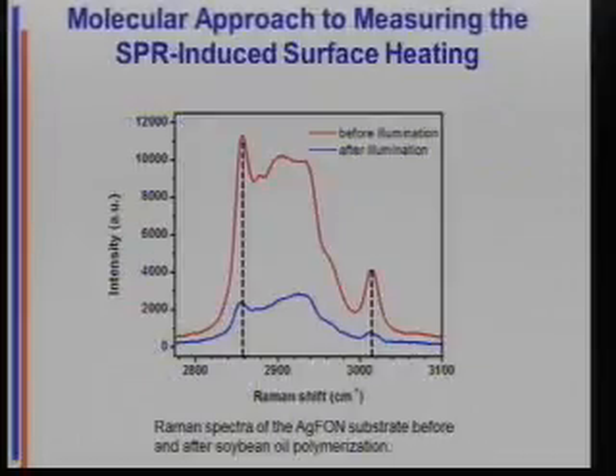And so then we come to how do you figure out what the temperature of the substrate surface is? We're talking about little bitty hotspots on little bitty nanoparticles. It's not a thermometer problem. It's not a thermocouple problem. So the answer turns out to be we're going to bracket it with chemical reactions that have known onset temperatures. Because people have cared about food oils for a long time and what temperature they start decomposing, these are like ag problems. It turns out that there is a known set of food oils that have onset temperatures for decomposition, and those temperatures are known.